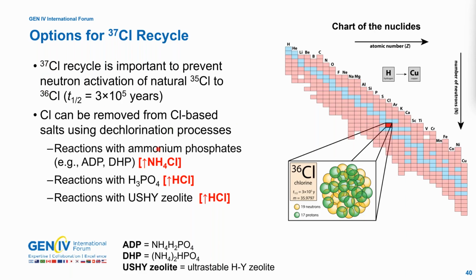And so options I mentioned for dehalogenation could include things like ammonium phosphates, like ammonium dihydrogen phosphate or diammonium hydrogen phosphate, to yield ammonium chloride. You can also react with phosphoric acid or the hydrogen zeolite to create hydrochloric acid, where the chlorine 37 could then be recycled into subsequent batches of salt.